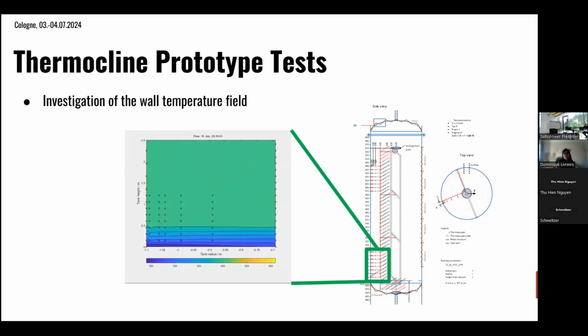Was that a question? Okay, and from this data, we were then able to create a two-dimensional animation of the temperature profile. And apparently, opposed to our expectation, there was a very homogeneous temperature stratification, even in the near tank wall region. So there was not a huge gradient to the outside of the tank wall.